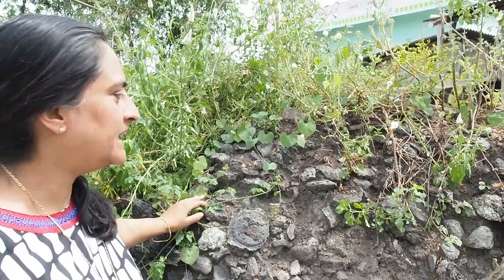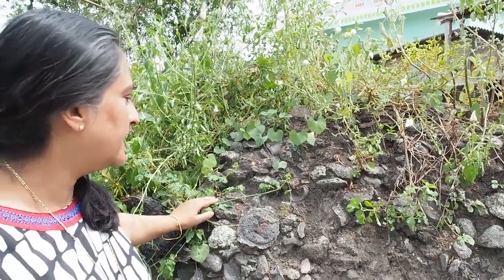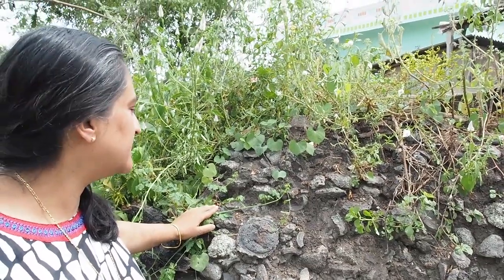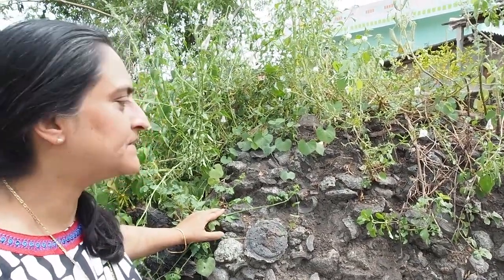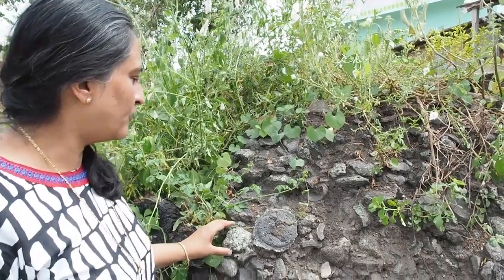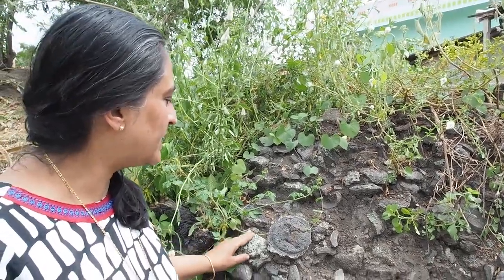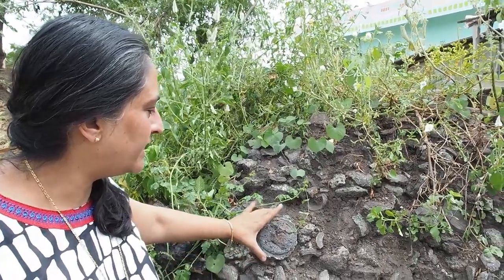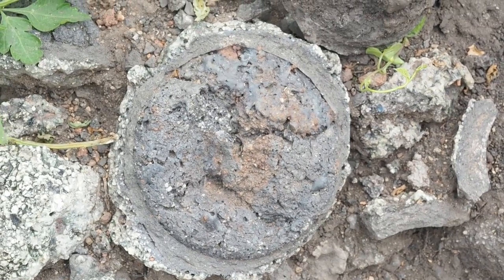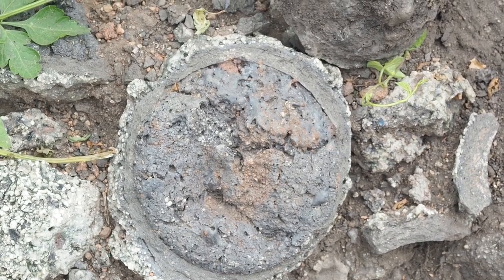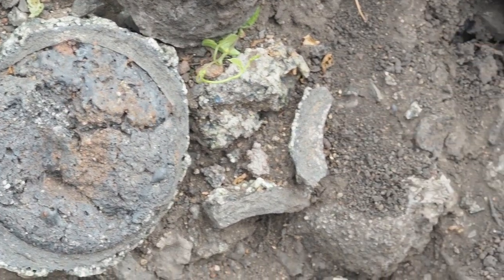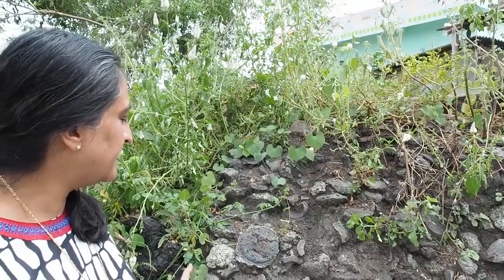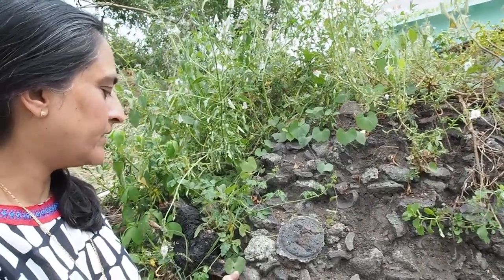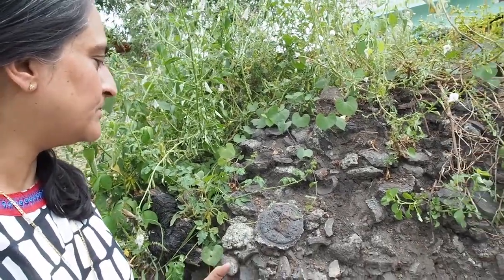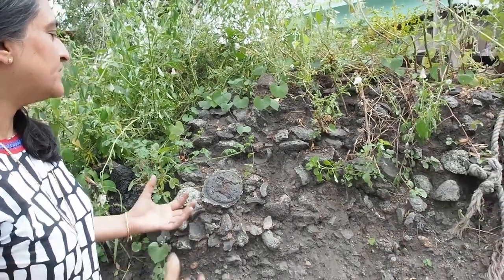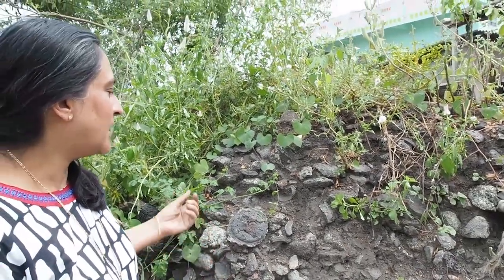Although many of the slag heaps and production sites are disappearing, in this little village of Konapuram, you still see remnants of the slag heaps, where you see the remains of the production of steel by crucible processes. Here you're looking at one of the bases or tops of the crucibles. You still see the streaks of rusted iron on it. And typically the wrought iron bloom would have been kept in the crucible and then heated to very high temperatures so that it was carburized to steel.